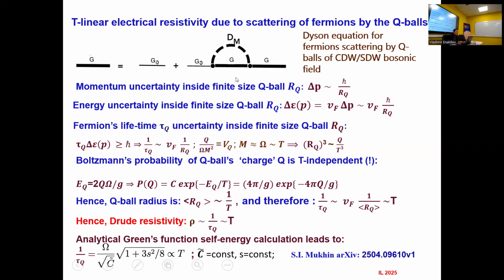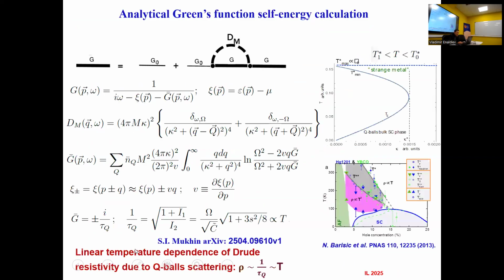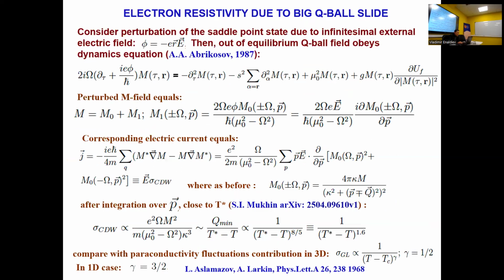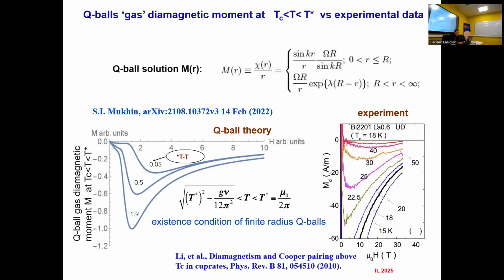And if you do this diagram and you can sum it to all orders just self-consistently, you get indeed that the inverse lifetime of not paired electrons really is linear in temperature in the regions where amplitude m is linear in temperature. And what is even more important, as we have seen, m just nearly equals omega without coefficients. So you see that this 1 over tau just equals omega without coefficients. More detailed calculation, which is now on arXiv here, indeed gives this answer. So just Matsubara omega appears with some numerical coefficients. And these are details of calculations, but as I have no time to tell now